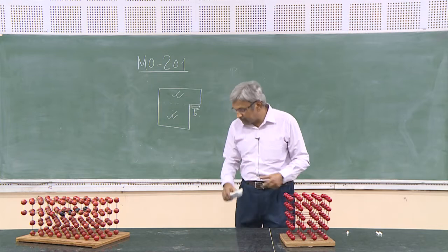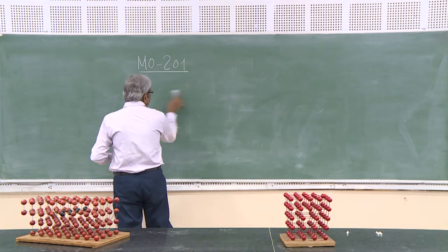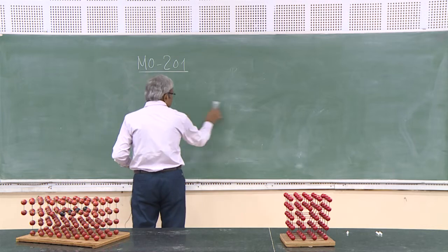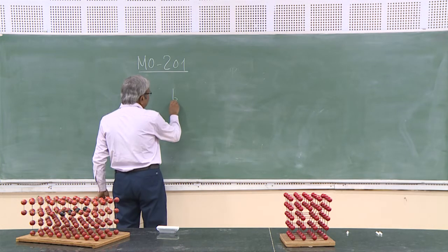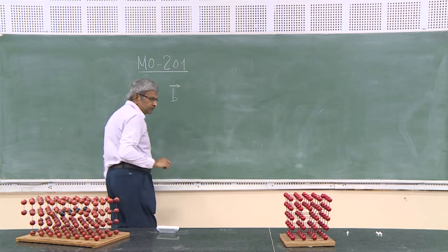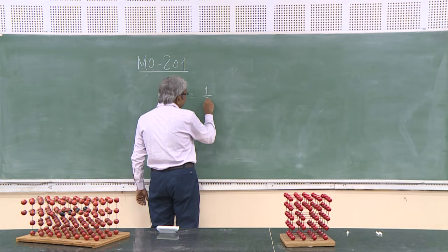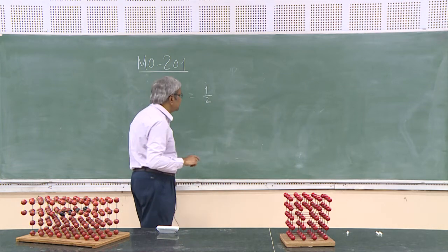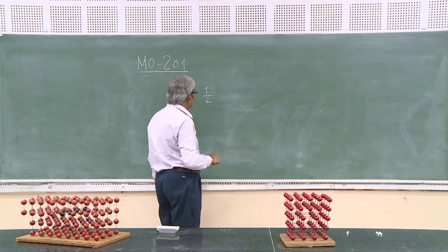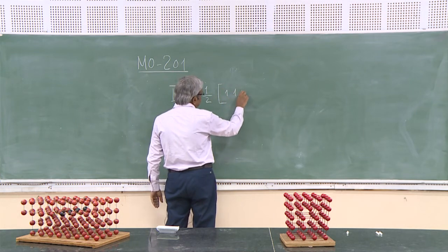As I have told you in the class, I repeat it again that the Burgers vector of a dislocation for a CCP structure, cubic close packed structure, is the nearest approach between two atoms in the CCP structure, one atom per lattice point, and this is how we had written.